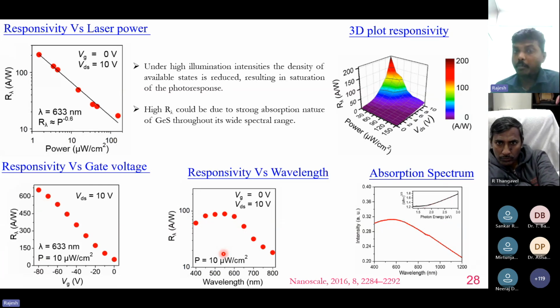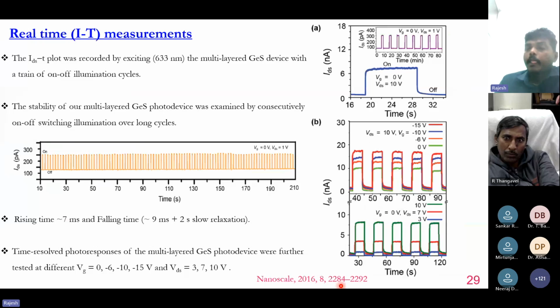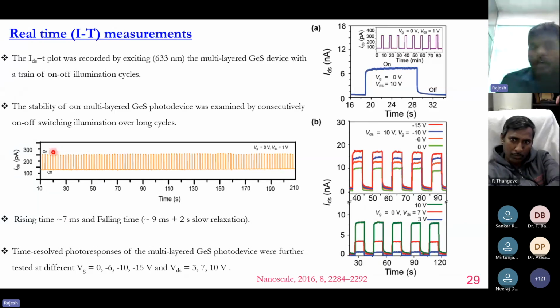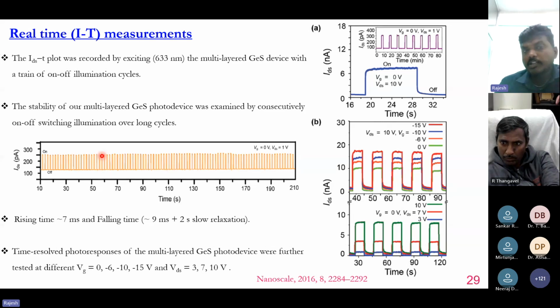And we also tried to demonstrate a broadband absorbance of our material. So we performed photodetection from the visible region, from 400 to 800 nanometer. We showed that this germanium sulfide can act as a broadband photodetector. And we showed a real-time application by shining light on and off for a large time interval. We can clearly observe there's no degradation in the on-off cycle during light on and off. It clearly indicates our germanium sulfide is a stable candidate in ambient conditions.